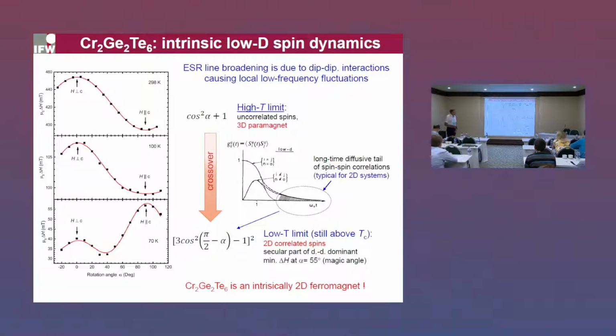However, in the 2D limit, where this diffusive tail is prominent, only one part, the so-called secular part of the dipole-dipole interaction, is present and survives, and it has a very distinct angular dependence. This is 3 cosine squared minus 1. So one no longer has a minimum and maximum in these extreme directions of the field, but a minimum at the so-called magic angle of 54 degrees. This was the second evidence that chromium germanium telluride is an intrinsic two-dimensional ferromagnet in the bulk limit.